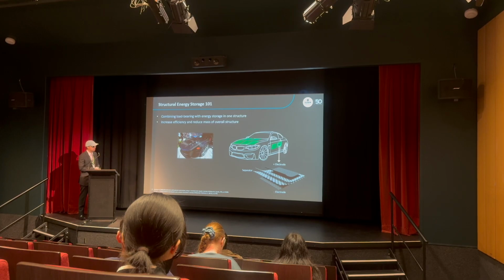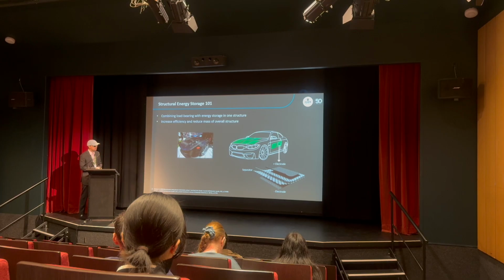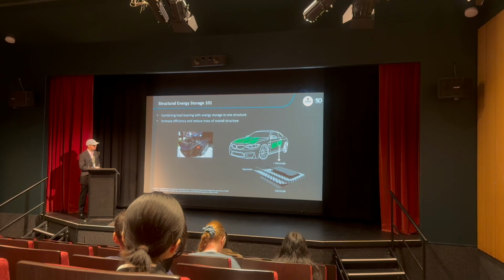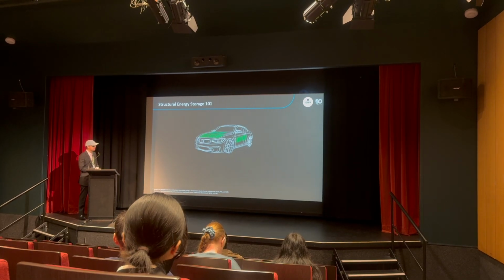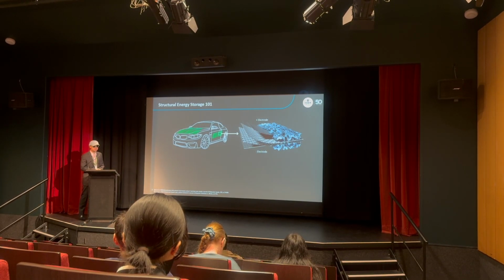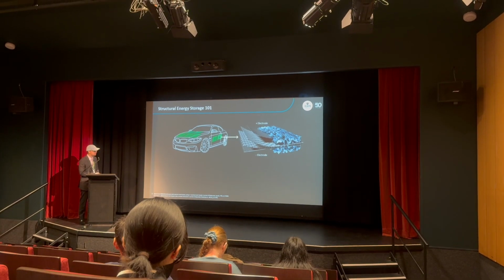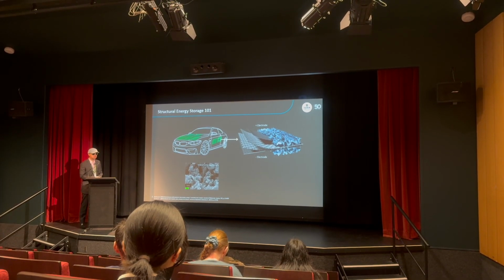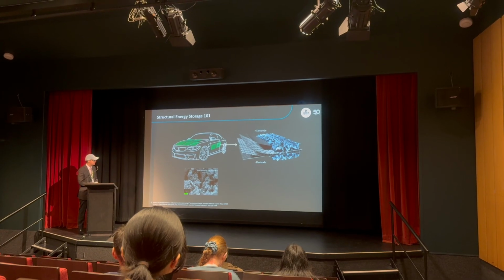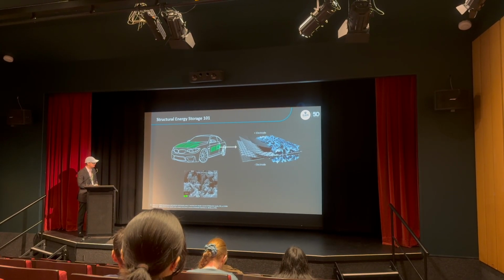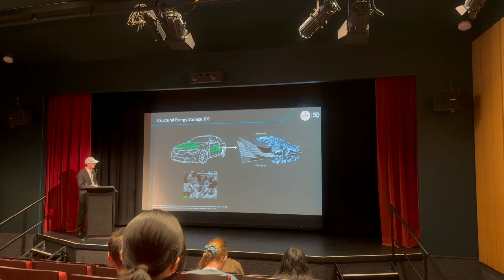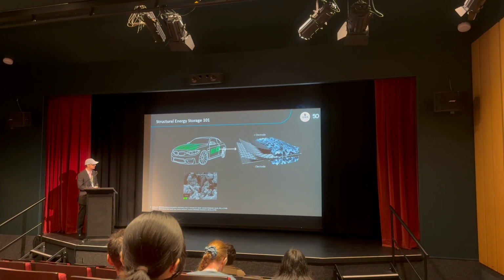This is what a multifunctional structural capacitor device looks like. You have two layers of conductive carbon fibre that act as electrodes, and they are held apart by a glass fibre separator. This system is held together by a bicontinuous two-phase solid polymer electrolyte. This is what the solid polymer electrolyte looks like under scanning electron microscopy. You can see within this porous network is basically where the conductive ionic liquid sits, and the porous resin that you can see there is the solid phase that acts as the mechanical phase.